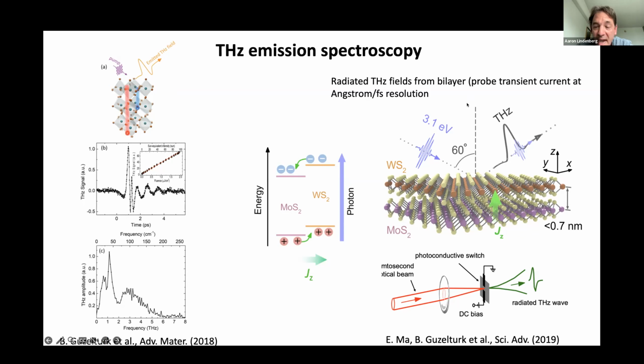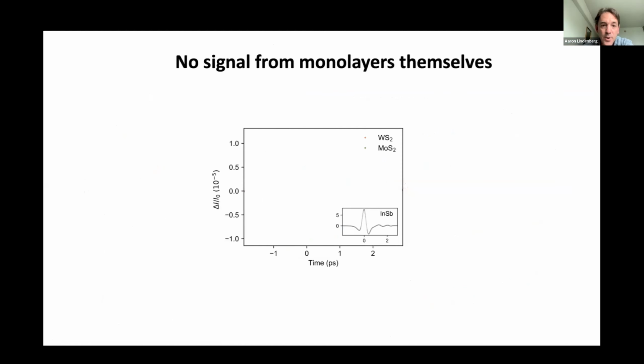And we said, all right, do we have enough signal to noise to really probe the current from a bilayer, probe this transient current at angstrom length scales at femtosecond time resolution? So the experiment is pretty simple. We come in with a 400 nanometer pulse. This is a WS2, MoS2 heterojunction, and we record, using electro-optic sampling, the radiated terahertz field coming from the sample.